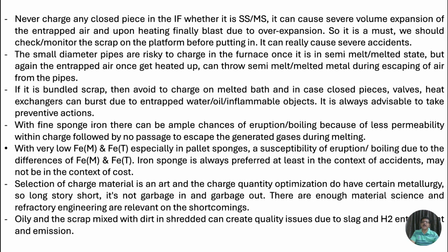Small diameter pipes are risky to charge in the furnace once it is in semi-melt or melted state. Again, the entrapped air, once heated up, can throw semi-melt or melted metal through escaping of air from the pipes. If it is bundled scrap, then avoid charging on a melted bath, and in the case of closed pieces, valves, heat exchangers can burst due to entrapped water, oil, inflammable objects. It is always advisable to take preventive actions.